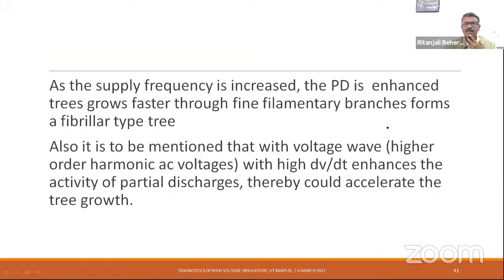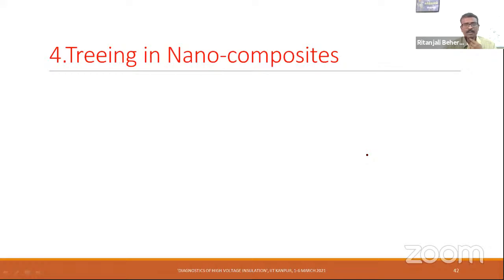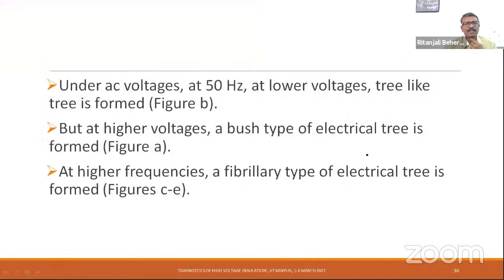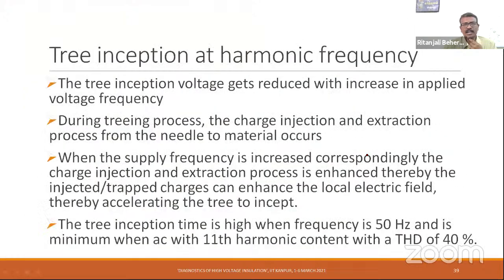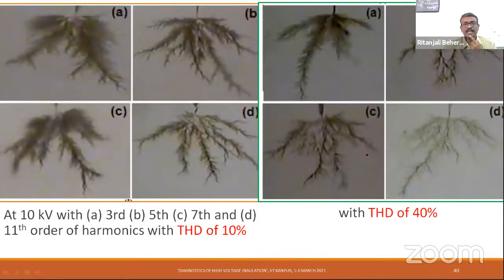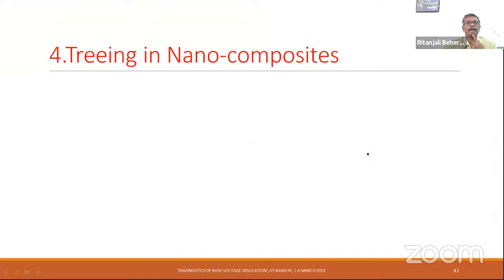And it is to be mentioned that with the voltage wave with the higher harmonic voltages, with a high dV by dt, this enhances the partial discharge activity. This could accelerate the tree growth. So that is a little bit about the trees at AC with harmonic frequency.